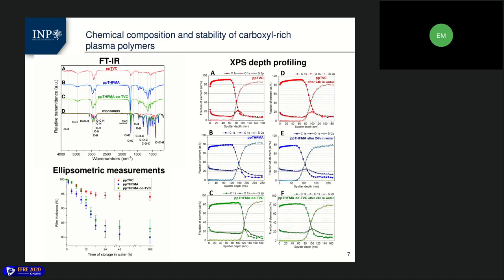Also, ellipsometric measurements were conducted to determine the film thickness loss after storage in water. So for TVC, THFMA, and copolymer film, the losses were 6%, 18%, and 16% respectively. Within the further 168 hours of storage in water, no more significant changes in thickness were recorded.